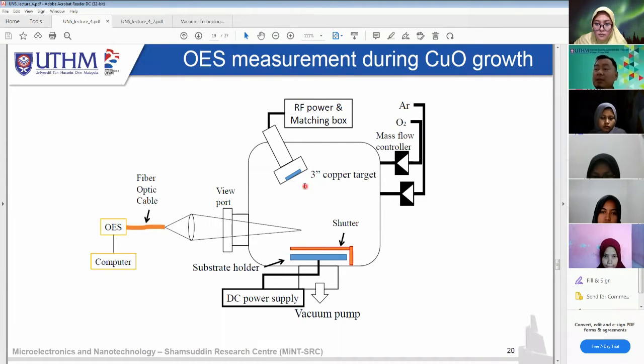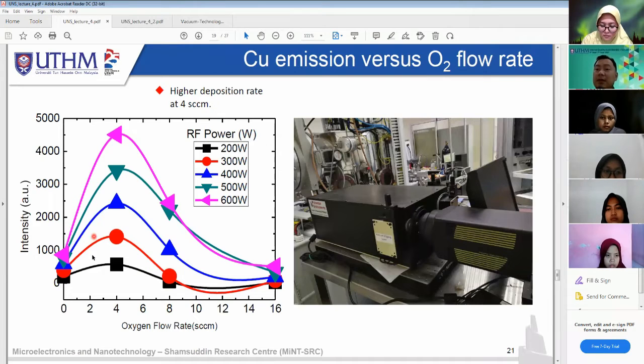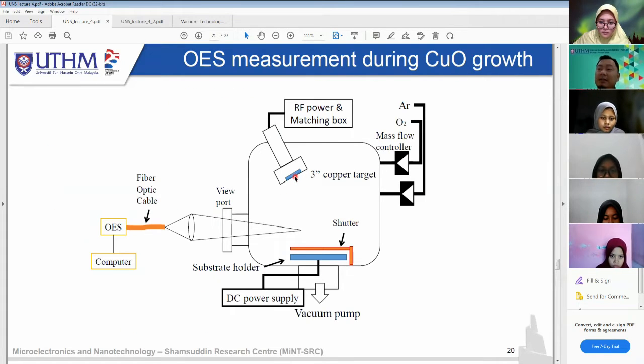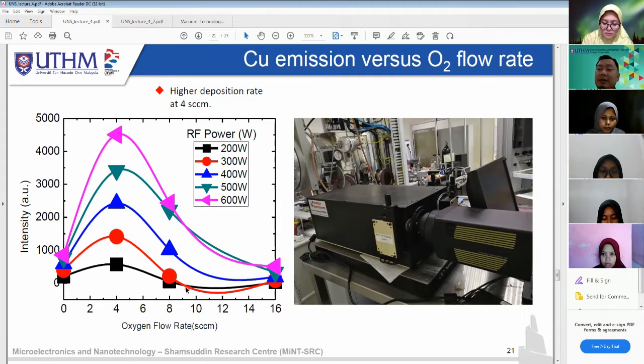We change the target to copper, and then we have oxygen and argon flow so that we can create a thin film of CuO. So this is the result, where we can see that when we change the flow of the oxygen, the intensity is changing. This is a copper emission. So we can select what we want to observe. In this case, we observe the copper. Meaning when we add too much oxygen to the chamber, the copper cannot be released from the target. In this case, we use the copper as a sputter target, so we capture it over here. You can see the copper intensity is changing based on the power supply and the oxygen flow rate. So this is how we can monitor or control our chamber.